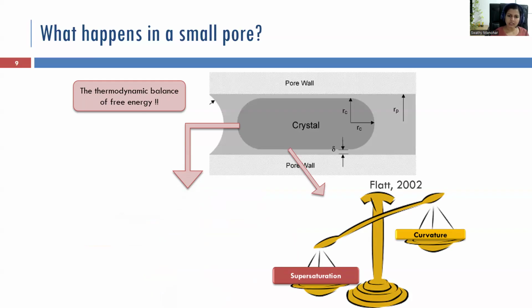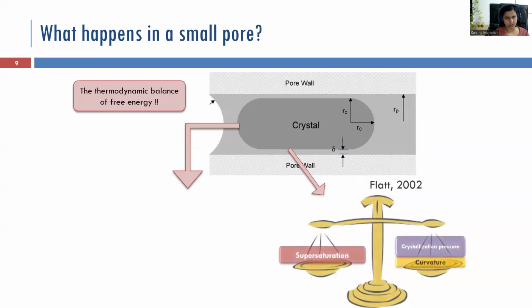So the Gibbs free energy associated with this excess unwanted supersaturation at this place will generate some crystallization pressure acting on the pore walls. Now this crystallization pressure and the smaller curvature is going to balance the high supersaturation here.